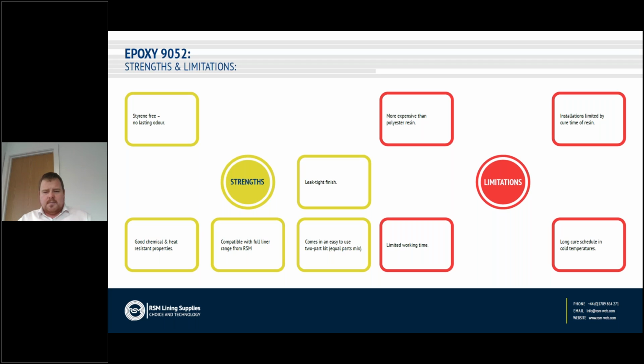The product can be accelerated in terms of the cure through the use of a hot box or small amount of hot water. Possibly one of the only other limitations with 9052 as a product is that in cold temperatures it can be a little bit difficult to work with, as if you can't get hot water there, the cure time is rather excessive, over sort of 4 to 5 hours in cold temperatures.